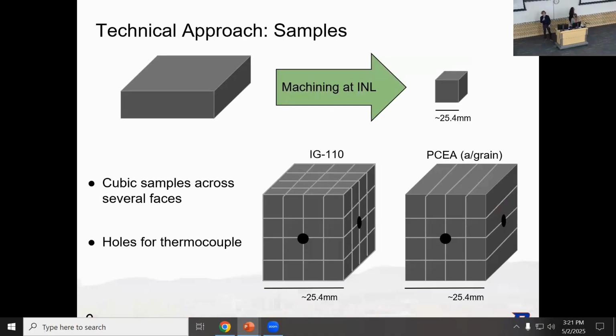Before we start getting into any part of the experimental setup, we first need our samples made. All of our samples were manufactured at the Idaho National Laboratory IRC complex in 1-inch cubes. There were two main reasons for choosing the cubic geometry. The first and most important reason was we needed flat faces for our emissivity measurements. The other reason was we needed a nice flat base to prevent our sample from rolling around in the experimental setup.